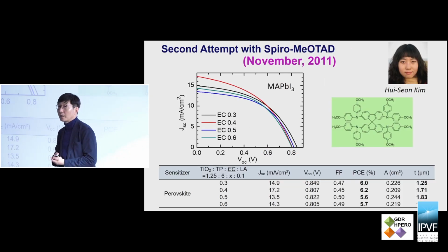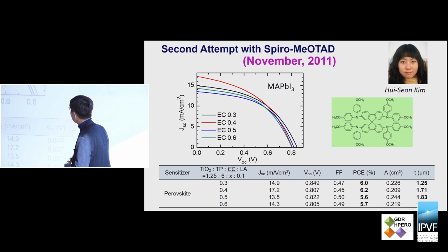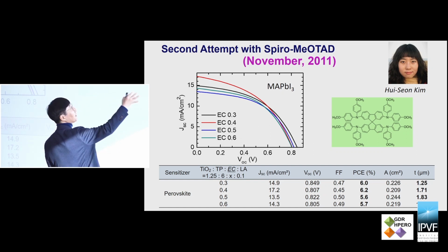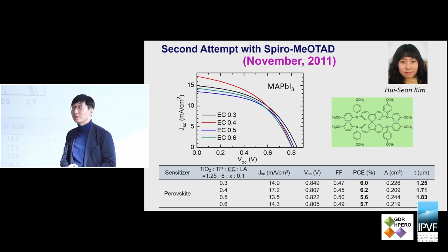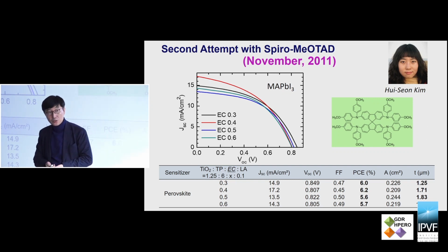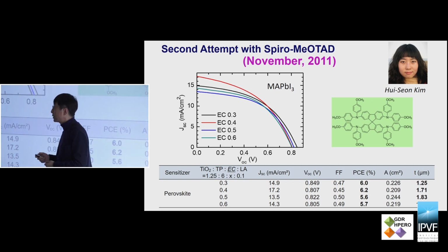So we switched from polymer to molecular-structure hole conducting materials here. And then the efficiency here, anyway, was around 6%, and we changed some pore structure and also the titanium oxide film thickness, something like that, but we could not increase the efficiency. So at that time we were suffering with improving the efficiency using solid hole conducting materials.